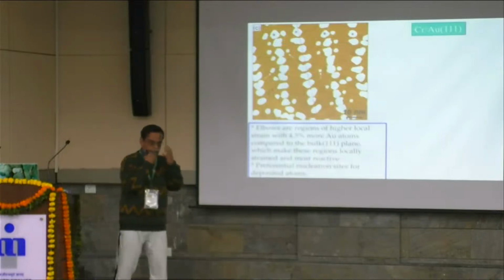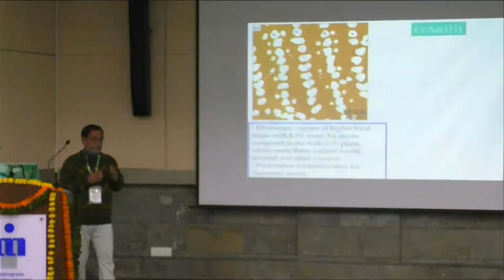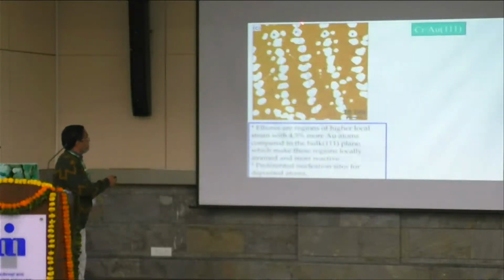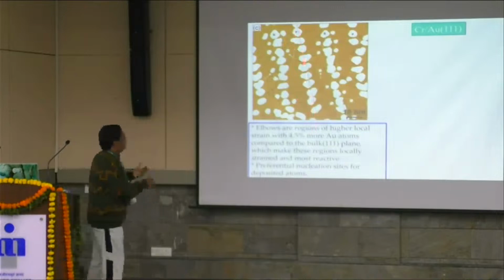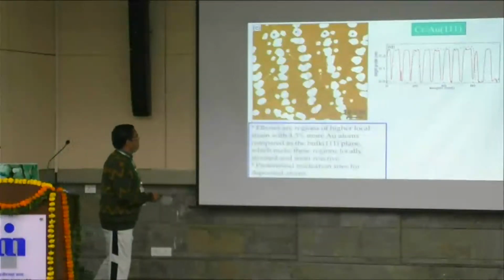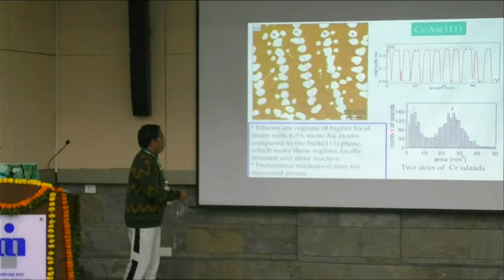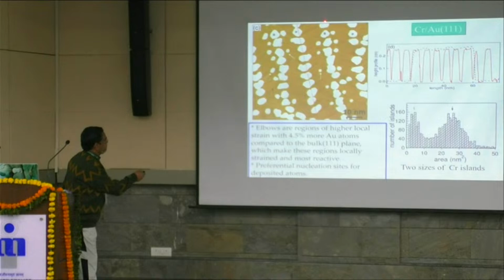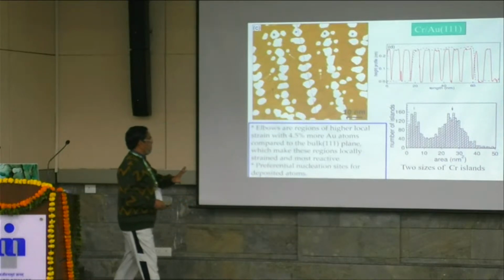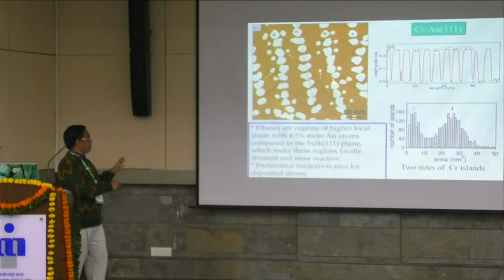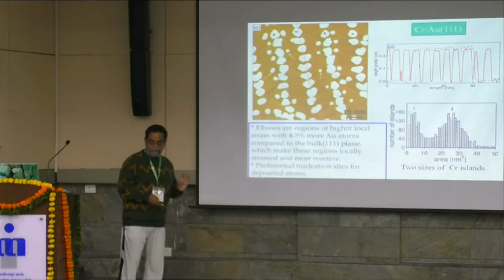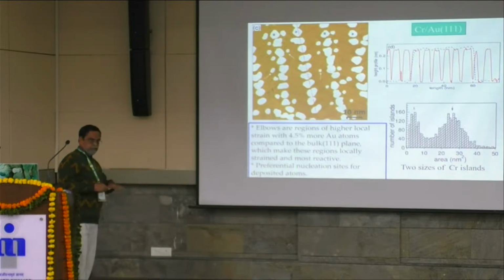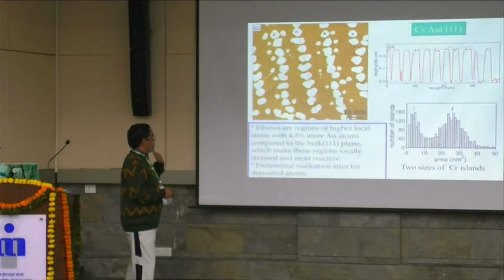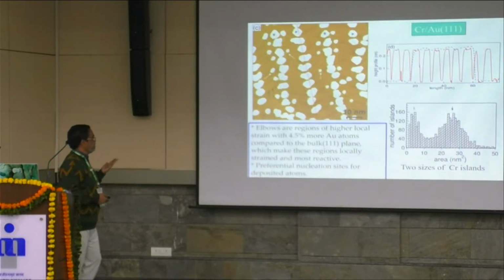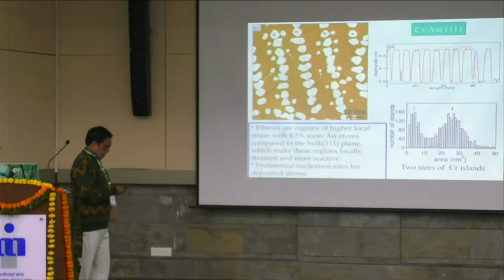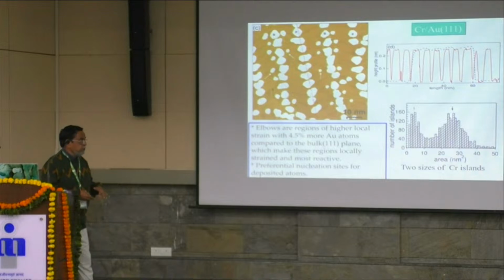The reason is that these elbows are more reactive, because there are more gold atoms compressed in that region, and that's why the chromium comes. So that template of gold makes them ordered. These are all atomic step heights, and also there are two types of sizes. One is this small size, and another is this big size. I will not go into the details, because the herringbone reconstruction changes, and because of this change, the second type of smaller chromium islands come up. So this way, using the template of the reconstructed gold, we can make ordered chromium or any other, manganese also, nano islands on the surface. So these are the kind of nanomaterials which are grown in UHV on a surface.